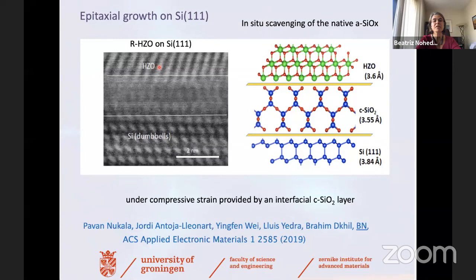The same hafnia material, zirconia hafnia, is scavenging the oxygen from the silicon and creating a crystalline silicon oxide monolayer that is able to organize the hafnia in a very nice rhombohedral manner. This interface layer also provides the compressive strain that is needed to create this polar phase.